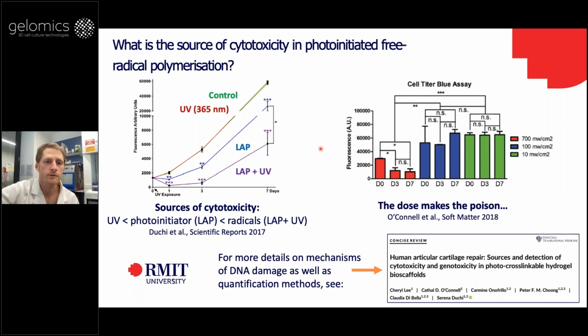So we've studied before also, we can calculate, like I said, the free radical flux, and we know that when we do that kind of experiment where we control the rate of free radical production and assess how that's affecting cells, we find an obvious and huge difference, where the lower light intensity results in much lower loss of cells, even when the eventual stiffness of the materials is controlled. So that's another reason to use very low light intensity, the lower the better. You reduce that free radical flux, and that is the most toxic element that's affecting the cells, at least in our experiments. Okay, so I'll move quickly now because I think we're getting a bit late.